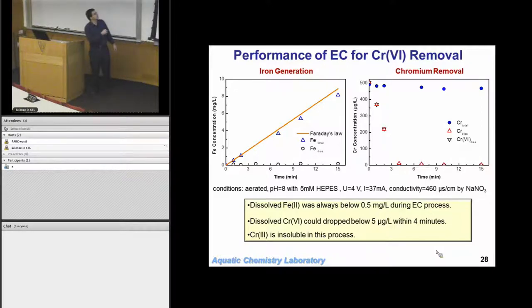This is what's happening with the iron. This is at pH 8. Total iron goes up, dissolved iron stays low. That means we're getting a lot of iron oxide particles. The dissolved chromium and dissolved chromium 6 are in the red and the black triangles. They track each other exactly. Within 4 minutes, we can drop the chromium from 500 micrograms per liter down to less than 5 micrograms per liter. Works really, really well.